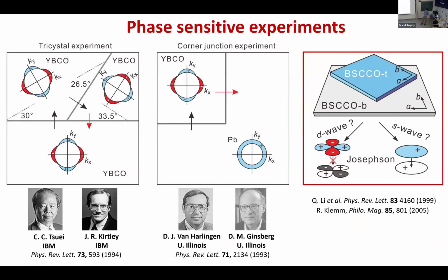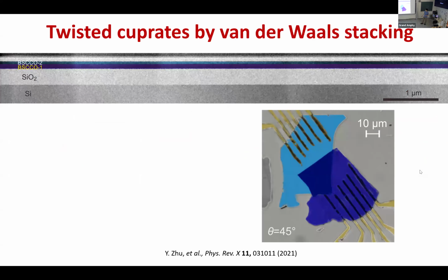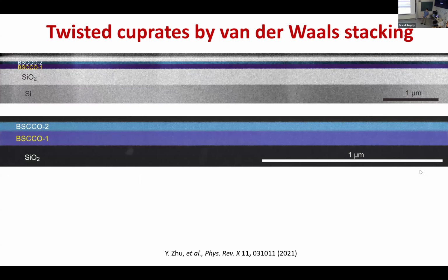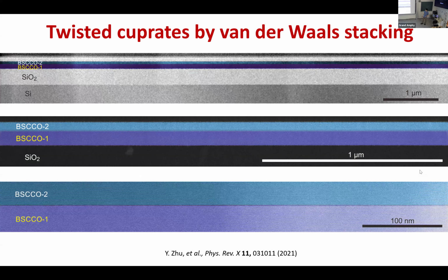Quite some years ago, we started to do this because we wanted to address the problem: if you have a twist between two cuprate flakes, because the cuprate has a natural insulating layer, we can address tunneling. If it's D wave, then the symmetry argument tells us that there shouldn't be any Josephson tunneling, and if it's S wave, there could be Josephson tunneling. We tried this by just doing the exploration. People did this before, but with bulk samples, and we just tried to revisit this issue now with exfoliated flakes.